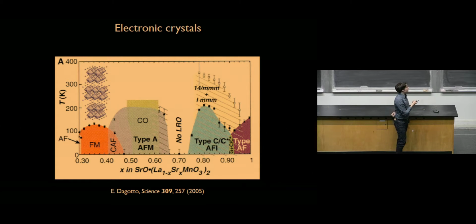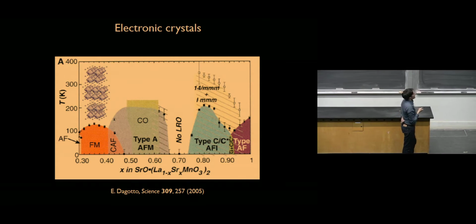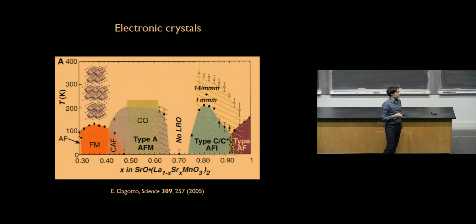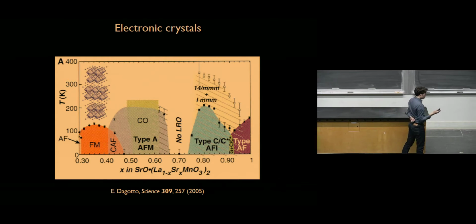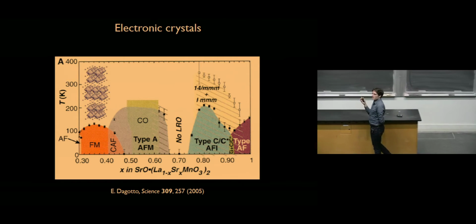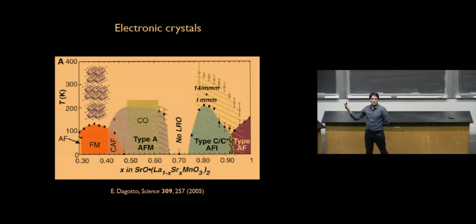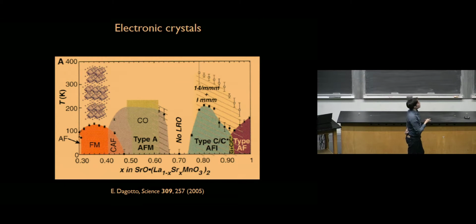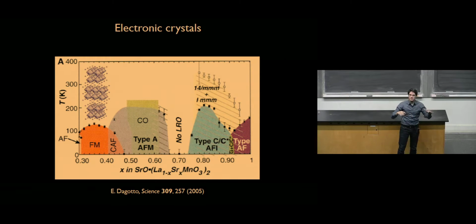Ferromagnetism, antiferromagnetism, canted antiferromagnetism, charge order, type A antiferromagnetism. This is a special region where there is no long-range order. This is, again, an antiferromagnetic insulator. Some of these acronyms, I'm not even sure what they mean, to be honest with you. But the point I'm trying to make here is that it's a very rich phenomenology. So you end up with this very colorful phase diagram, typically in quantum materials, because you have multiple electronic orders. Each of them has some energy. The one that has the lowest energy typically wins, and is the one that you find experimentally to occur in your sample. As you tune experimental parameters, you tip the balance between different electronic phases or different electronic orders.